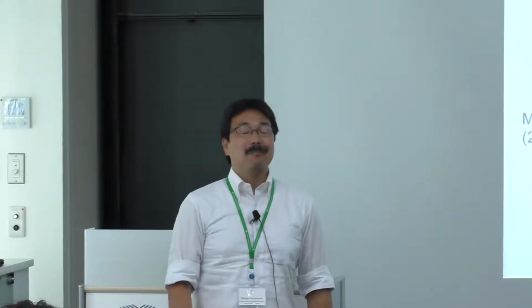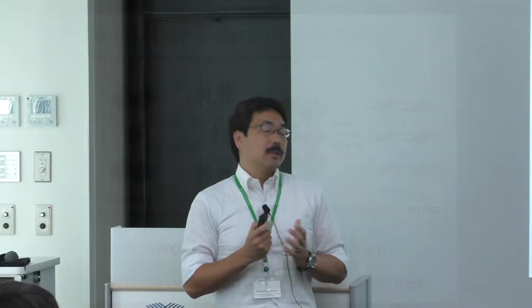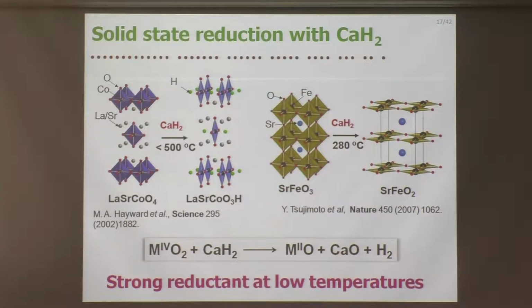For most of the people here, CaH₂, calcium hydride, is an unfamiliar material. However, nowadays calcium hydride is used in rational material synthesis - some examples are shown here. Anyway, the most important feature of the reaction with calcium hydride is that we can get very strong reducing ability, especially at low temperatures. So we want to take advantage of this.